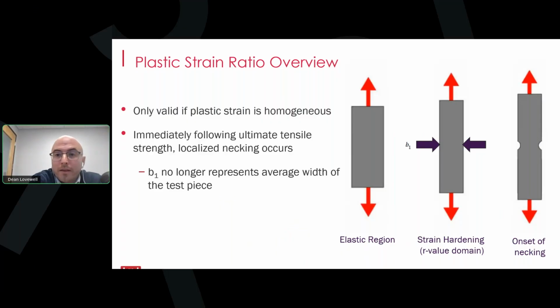Now, the important takeaway that I really want to emphasize here is that once tensile strength is determined, so the maximum force has occurred, and after which you have the onset of necking, we can no longer use the R value formulas from ASTM and ISO. This is because the resulting width is no longer reflective of the width of the reduced section. This is because after necking, all of the width strain now occurs where the neck has started.